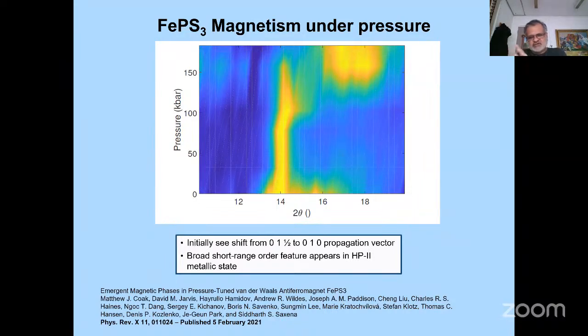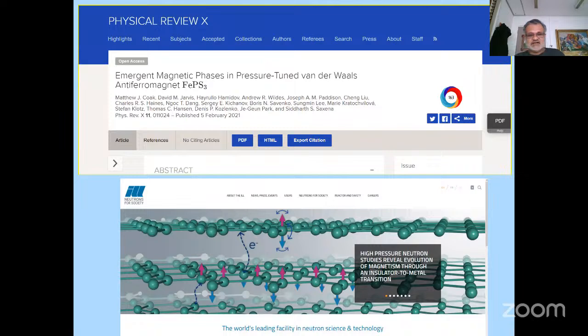So it's now more of a short range order, harking back to what iron looked like as we discussed in the beginning of the talk. And we can track that with neutrons. This was a result which ILL liked very much. They put it on their front page, and they showed how these interactions, which we could measure through neutrons, are causing this new phenomenon.